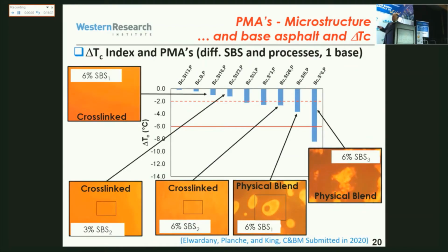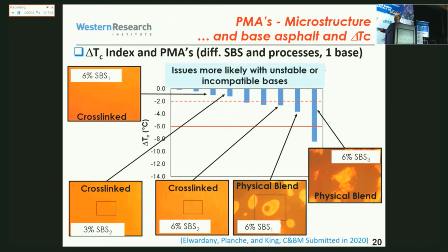We looked at whether there is a relationship between the microstructure and the delta TC, and yes, we found one. That's by data mining, and I don't have time to go into details. But this shows very homogeneous binders, cross-linked for example, though they could also be not cross-linked. Those are cross-linked, at a less negative delta TC. Whereas this one, which is heterogeneous, has a very low delta TC. So there is a relationship there, all right?